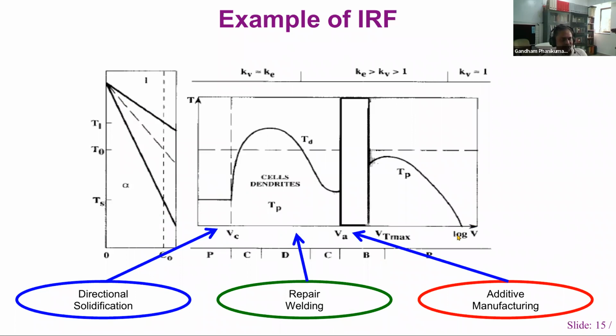As you increase the velocity on the x-axis, the interface temperature is on the y-axis. And the thumb rule that I want to tell you is that whichever curve has a higher value, that is the kind of morphology that is to be found. So here you can see that the morphology of cells and dendrites is higher here. So that will be found for intermediate velocities. And the planar morphology has a curve here. So the planar morphology will be found. So whichever is higher will be the one that will be formed.